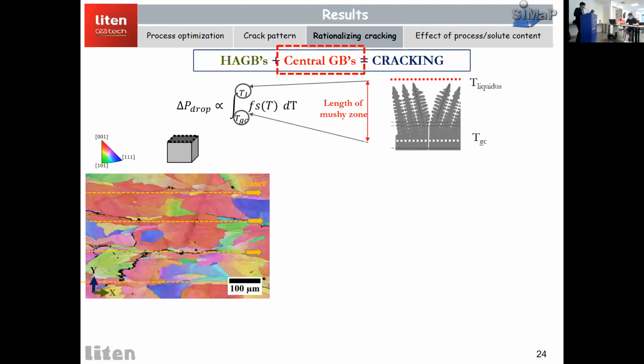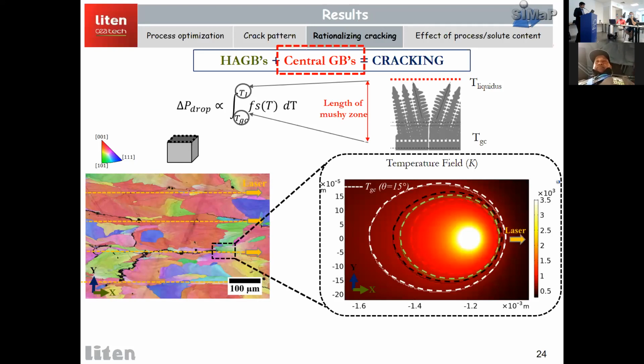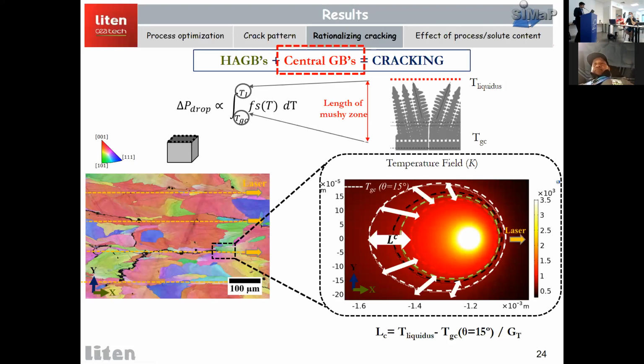So here, just to give you a reminder, is the top view EBSD image of our sample. The lasers are moving along the X direction here, and we clearly see that the cracks follow the laser tracks. So if we look at our horizontal simulation, the temperature fields in the vicinity of where the laser is moving, based on different contours, the liquidus and the coalescence contour here at 15 degrees, the white contour, we can estimate the length of mushy zone by dividing by the thermal gradient for sure.